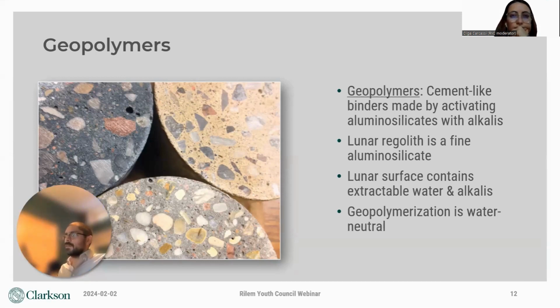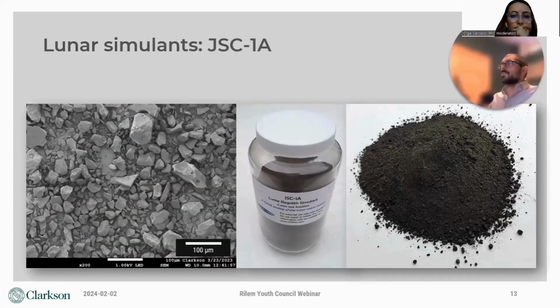Interestingly, the lunar surface also contains some extractable alkalis, so the activators could potentially be produced using the principles of ISRU. And finally, geopolymers do require water for mixing, for workability and consolidation, but the geopolymerization reaction is actually water neutral, so that water could potentially be recaptured. So lunar regolith-based geopolymers seem like a pretty promising solution.